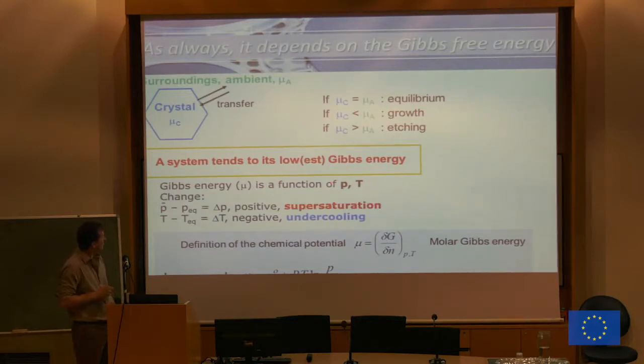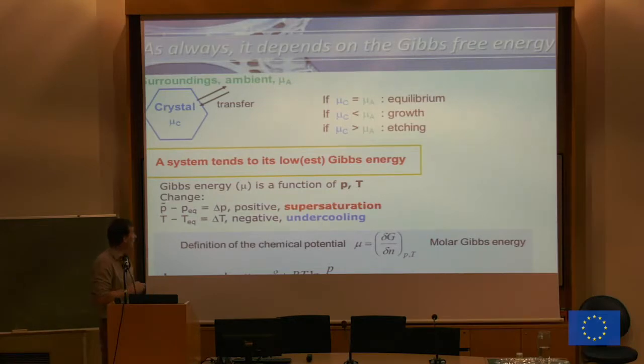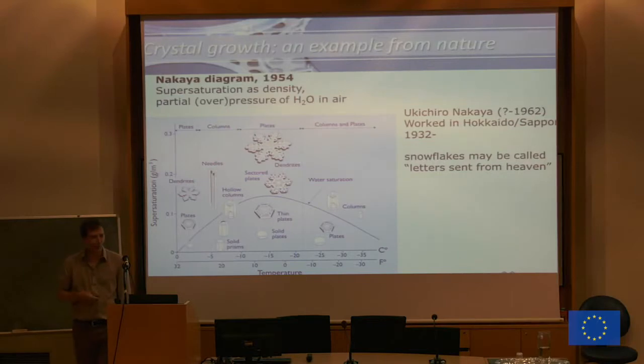Typically, the main things that we will work on to do crystal growth is we will work with a positive pressure differential between the ambient and the crystal, which we call supersaturation, and a negative temperature difference, which is undercooling. And with that, first a practical example. This is work that was done by this Japanese gentleman in the 60s, and he plots here as a function of undercooling and oversaturation of water in the gas phase, how you can grow snow crystals.